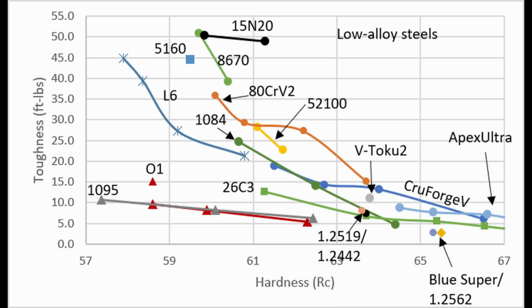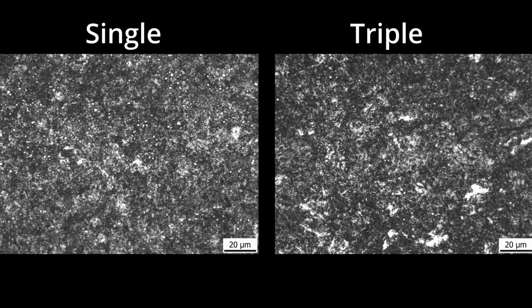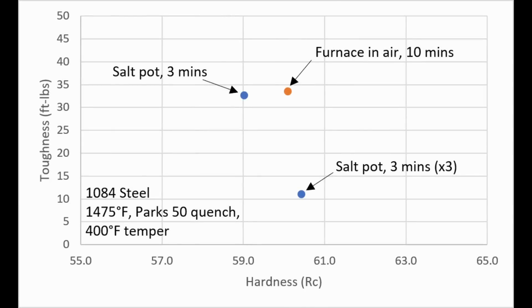Normally that's not an issue with 1084, but with the triple quench, you quench one time and now you have martensite. And when you start with martensite, the heat treatment response is much faster, just like we were talking about pearlite versus spheroidized carbide earlier. Martensite is the fastest starting structure to heat treat from. And so it looks like more carbide is being dissolved than just holding for a straight 9 minutes, by starting over with martensite and doing that twice. So the triple quench in this case, we ended up with excess carbon in solution, and the toughness went down significantly. Another thing to note is that the fracture grain was still very fine. The grain size was not affected by the triple quench, at least not in a negative way. Still very fine grain size, it's just the carbon in solution that led to the poorer toughness.